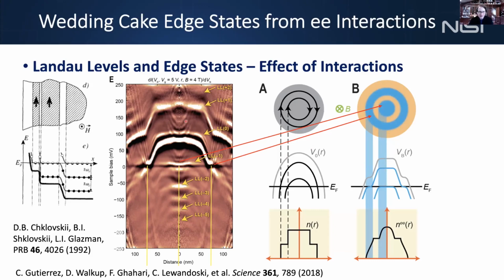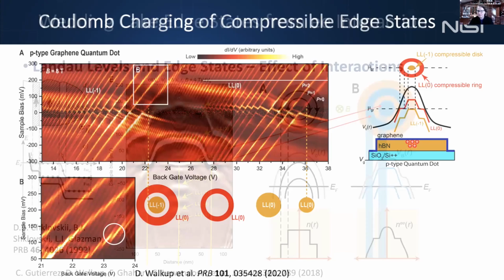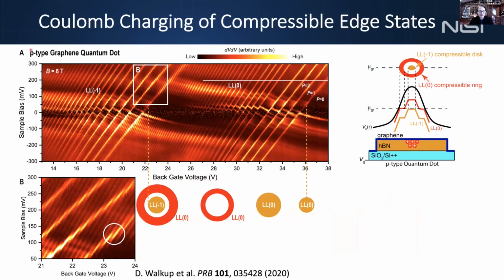And you can see that already by these faint lines. These are Coulomb charging lines, where you're seeing Coulomb charging of those compressible Coulomb islands. And if we go to 8 Tesla, that becomes dominant. So if I park the tip over the center of the island and I do this spectroscopic map again, you can see that the whole spectral map is dominated by Coulomb charging features instead of Landau levels. So Landau levels are even hard to see. They're these broad things here.